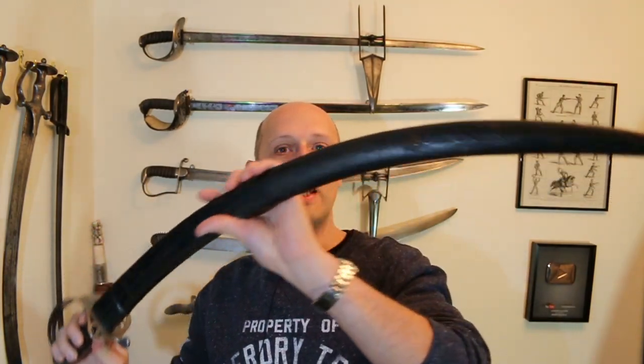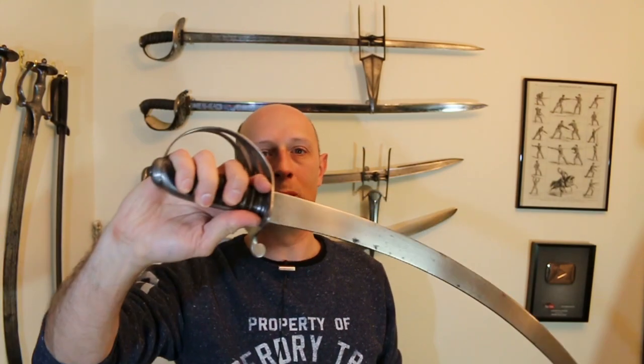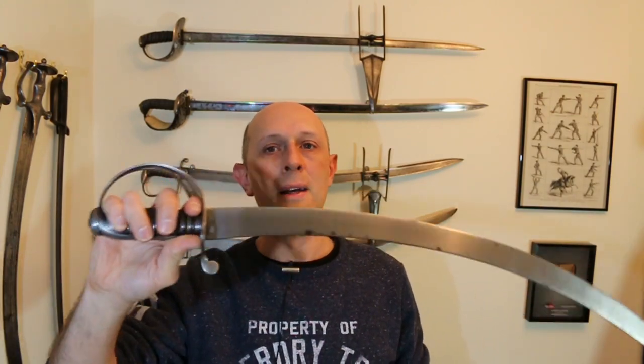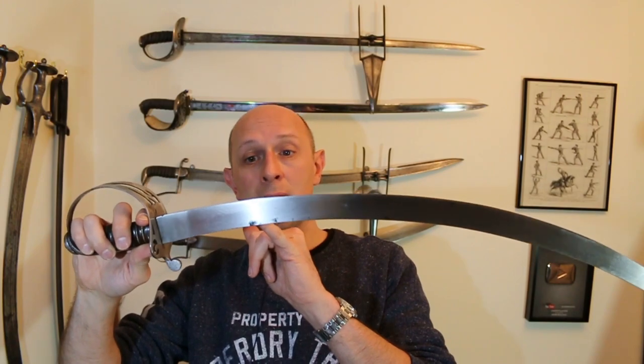But today I found something completely different. I've been doing test etching on various things and this sword has been a bit of a mystery to me for a long time because it's so curved and I thought that could be wootz. I did some test area etching on it without necessarily polishing it up or cleaning it as needs to be done for proper etching. I etched a little area and I did get a pattern, but it's not wootz — it's pattern welded.